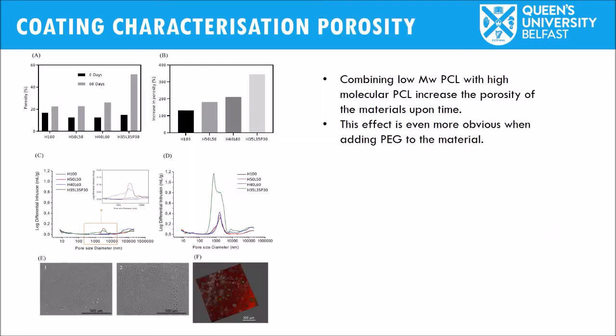Okay, so what we saw is that obviously the porosity of the implants increases as a function of time. Here you can see an example of a porous membrane at the beginning of the study, when it was freshly prepared, and after a few months, you can see that the porosity increased because of the biodegradable nature of the materials. In this case, you can see a microscopic image of this type of system, in which we have hydrophilic pores and a hydrophobic matrix. Okay, 2 different fluorescent dyes were used to highlight that, and basically the porous nature of these membranes makes them ideal for drug delivery purposes.